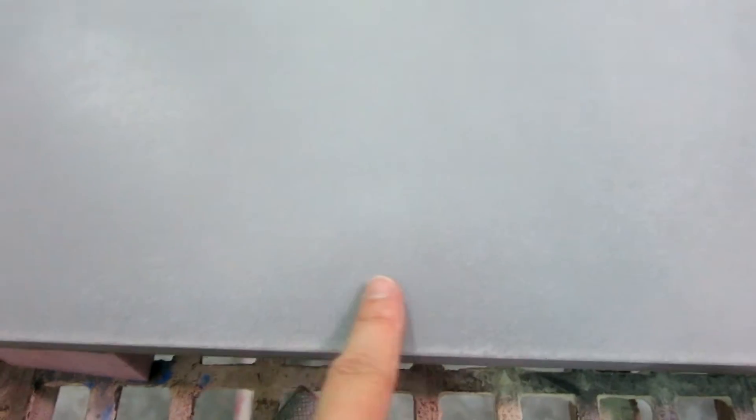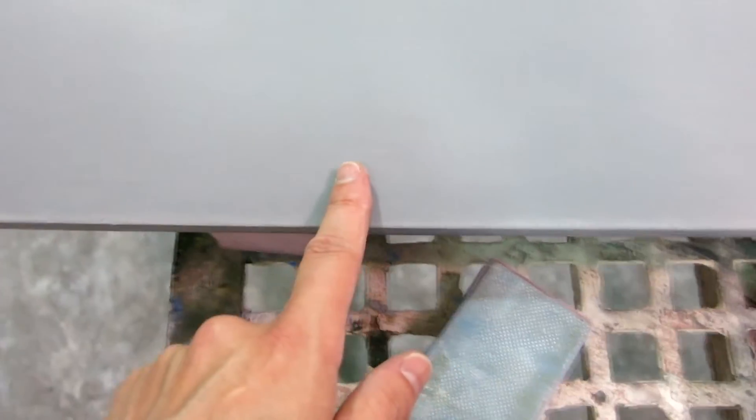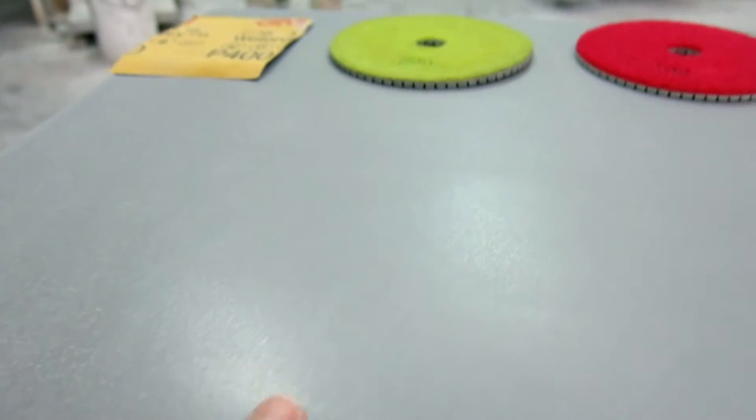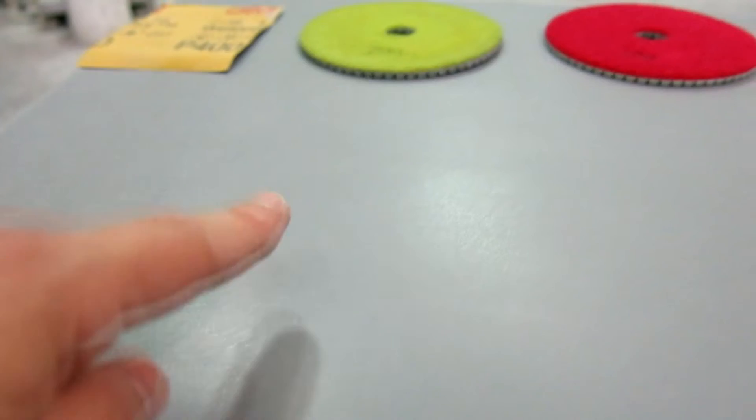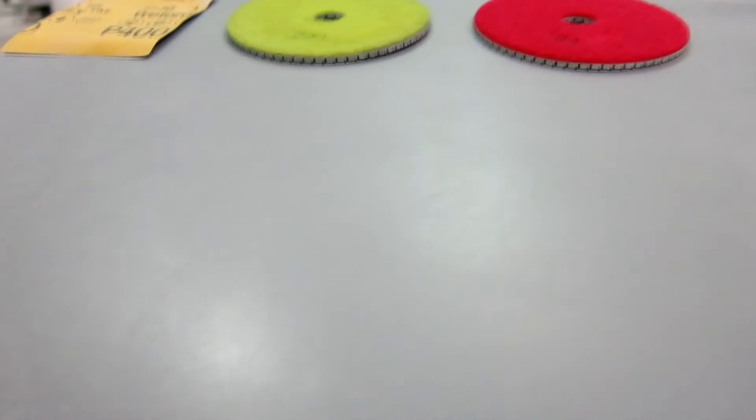This is the untouched surface. You can barely tell. But this is the 100 grit wet honed, wet sanded if you will. This is 200. Now you will notice there's a slight sheen from the 200 and the sheen is a lot lower with the 100. And there's the sheen of the as-cast. So it's very, very similar.